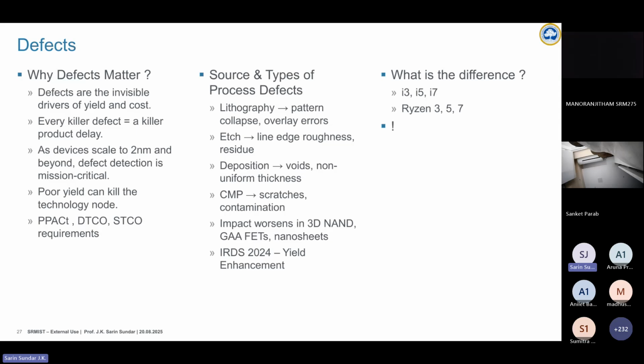So when you have more defects, they have to disable the cores. So if an i7 is an 8-core, they disable 2 cores, and the processor with more defects and fewer cores is the i3. So it's the same mask, same process, but when they do wafer mapping and find out the defects, accordingly they classify, because they cannot throw away the chip. They have to make sure it still works. You also see that in the pricing. But not all companies do that.